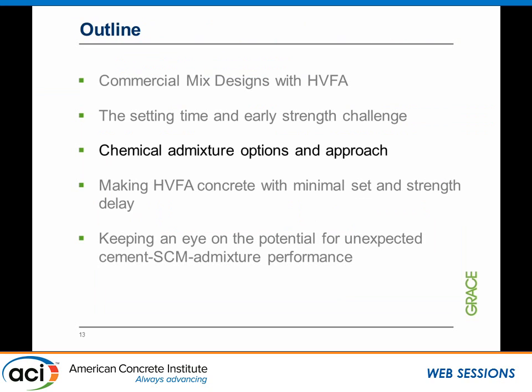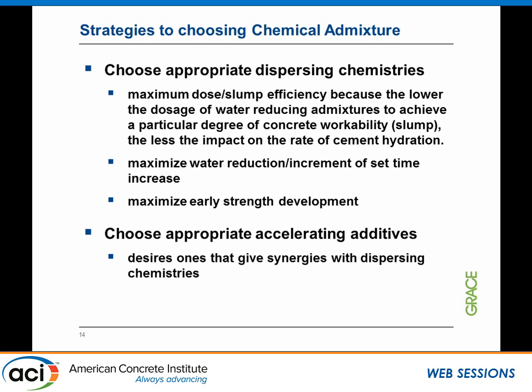So what are some options that we can do with the use of chemical admixtures, and how do we approach it? So when we think about using chemical admixtures, there are a variety of different chemistries that we can use. We think about what chemistry can give us the most slump with the least dosage. The reason for that is as you use less chemical in the mix, the chances for it to give you higher set times are going to be lower. And you want to maximize the water reduction relative to incremental set time, right? You want to have the least set time with the best slump increase, and you want to maximize early strength.